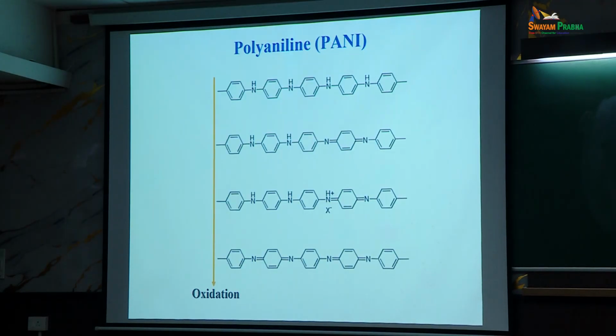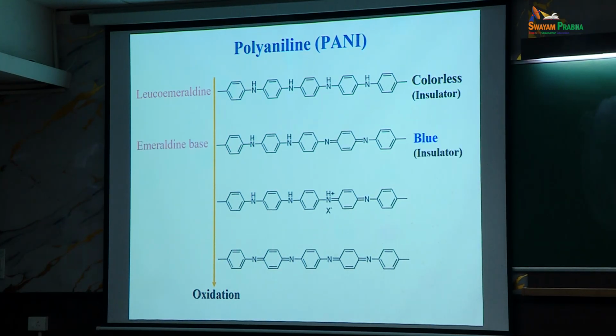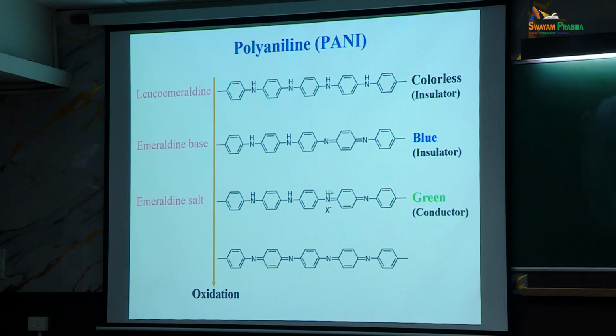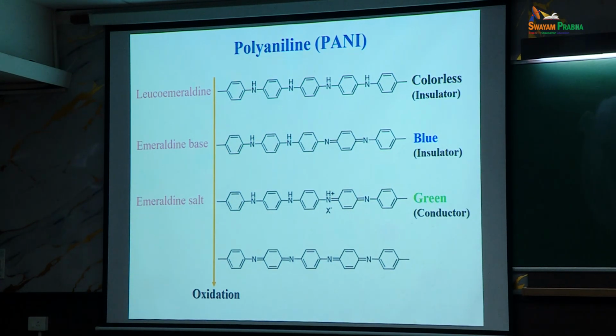And there are a lot of polymers. Polyaniline is one of the very stable ones, very easy to make. I don't know if I have a picture. And depending on the extent of oxidation, you can have colorless polymer. And if you oxidize it a little bit, you will get a blue polymer. If you make a salt of it, it will form green. And this is electrically conducting because you have a charge which can delocalize. If you over oxidize it, again, it becomes insulator. So you see the beauty of that. It's a polymer. Same thing, you just vary the oxidation.